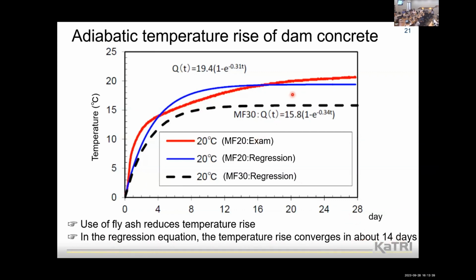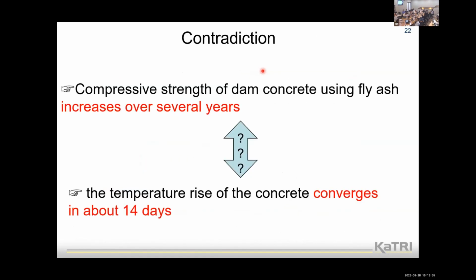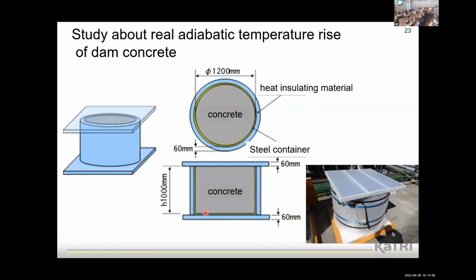That is estimated. So we use these equations when we try thermal stress simulation, thermal crack simulation, or thermal simulation. So that is a contradiction. Compressive strength of dam concrete using fly ash increases over several years, but temperature rise of the concrete converges over 14 days. That is a contradiction.